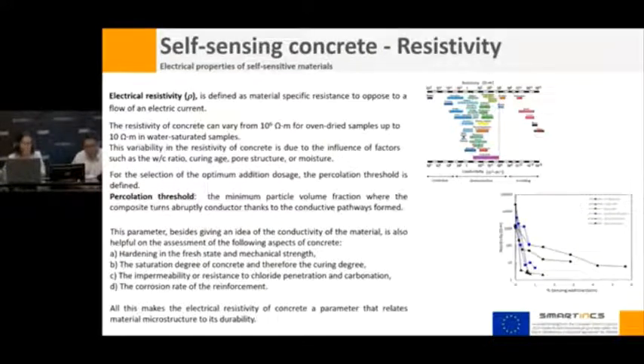Also, for example, if supplementary cementitious materials are used, the permeability of the mixture changes, increasing the resistivity value of that mix. As other colleagues presented in the morning session, this parameter gives an idea about the conductivity of the material, but it is also used in the assessment of the durability of concrete. Here, in our study, we use the resistivity measure for the selection of the optimum addition dosages.